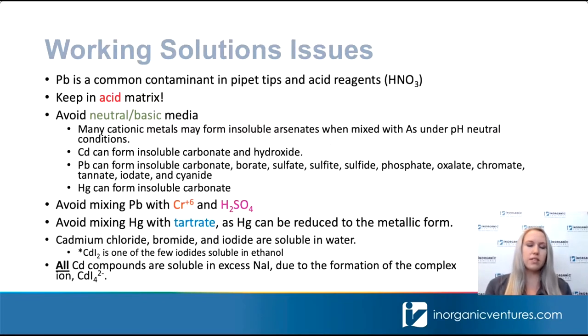Now let's talk about the stability of these elements in your working solutions. The first thing I want to mention is that lead is a common contaminant in pipette tips and acid reagents, specifically nitric acid. So make sure that you are using the cleanest materials you can, the cleanest reagents you can, to prevent any contamination from these sources. For all of these elements, you are going to want to keep those in an acid matrix and avoid neutral to basic conditions, as this can cause some major issues for all of the elements' stability.